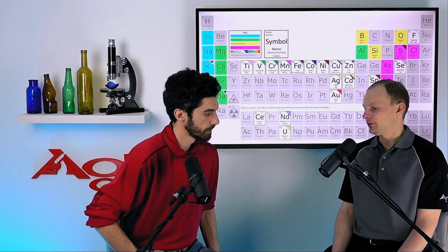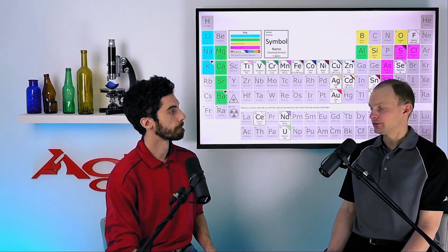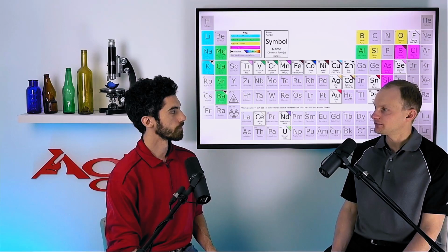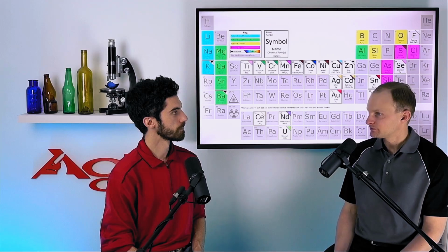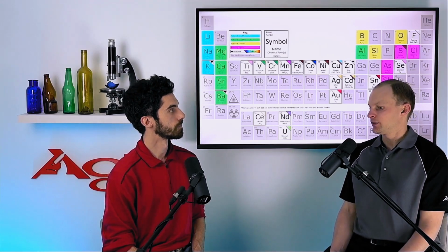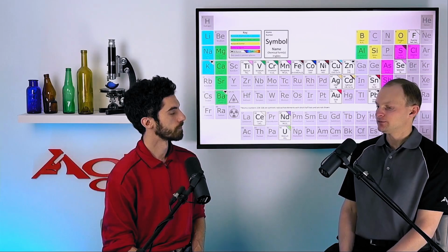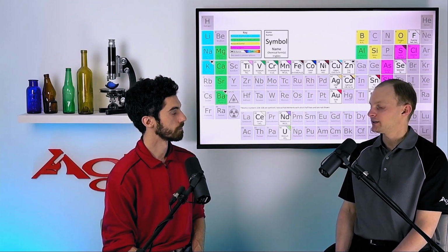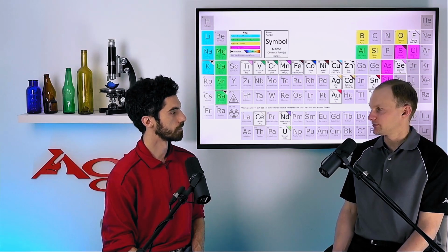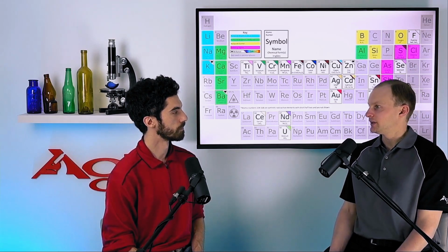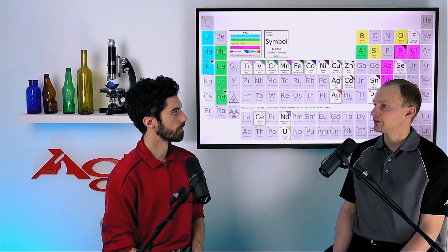Yeah, sure. Our lab in Maumee, Ohio, which is near Toledo, really handles analysis of bulk glass. So if you've made glass and you want to know what's in it, their most common technique is XRF, X-ray fluorescence, and that gives you pretty good accuracy down to fractions of a percent of the composition of the components in your glass. If you want to know about raw materials, they can do different types of tests. Some of them are more chemical analytical, where they have to dissolve things and titrate, and some can be done via the XRF technique to look at the purity of the components.